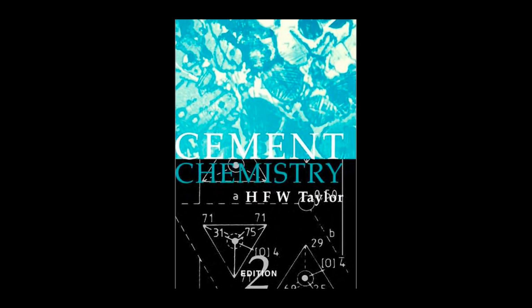And that rapid quench, which is often achieved by just spraying water onto the hot clinker, also results in the formation of a higher proportion of amorphous glass compared to a regular OPC. This glassy matrix helps trap any trace colorants away from the crystal structures. It's a high-cost, high-precision product that just shows how complex the basic material can be.